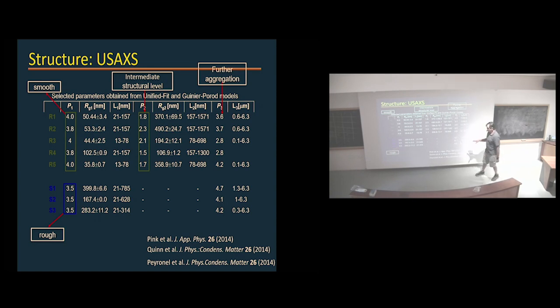While in this case, in the all-purpose shortening, you have a very large primary unit, or first structural level, with a rough surface. Think about many bumps, irregularities, on top of that nanoplatelet surface. And then you have a very large one, which is more related to a strange surface or a diffuse pore-like structure, depending on if you reach Schmidt or not. So the way I see it, you can have a gradual failure at different length scales, while in this case you accumulate all the stress and then you blow up. It's like an old Mustang versus a new Mustang. You better crash into the new Mustang. Otherwise, with this big piece of metal, you crash against the wall, it accumulates the energy, and then there's an explosive or catastrophic failure of the whole material, as opposed to the new cars that have more structural length scales. So that was our smaller units with smooth surfaces and 3 structural levels in the roll-in versus the other one.